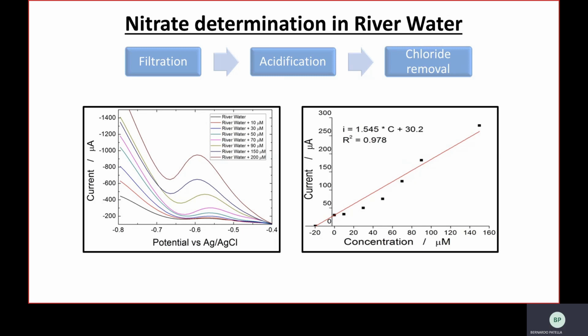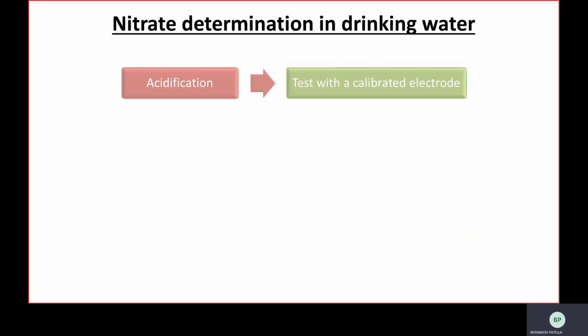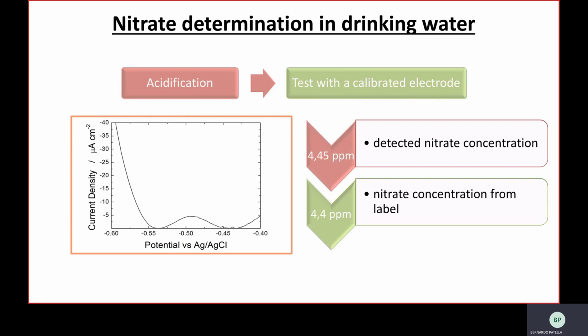nitrate was detected. This is an important result because it confirms the chloride removal and shows the applicability of the proposed sensor. Finally, a commercial drinking water was tested without the addition of silver sulfate, and 4.45 ppm of nitrate were detected. This value perfectly matches with the concentration in the datasheet of the water, showing again the applicability of